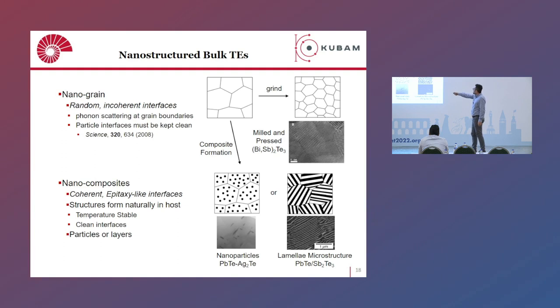So you can also, as I said, introduce some nanograins, which means, let's say this is your grain structure, you have these grain sizes, large grain size. For example, if you grind this, you can create smaller grain size, which means you introduce a lot of grain boundaries, you increase the grain boundary density, and this is scattering more of the heat-carrying phonons and it can lower the thermal conductivity.